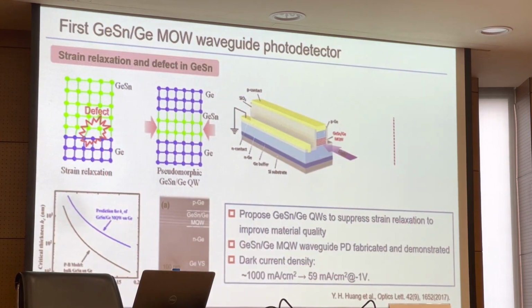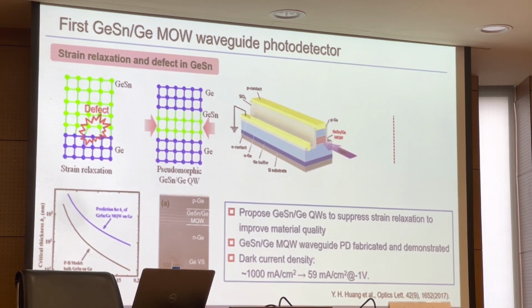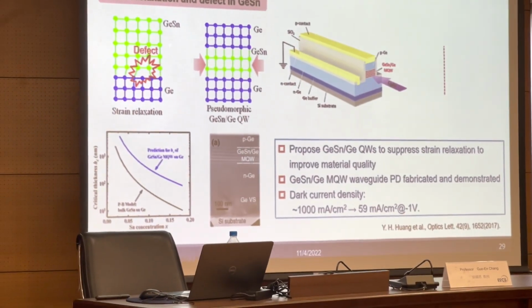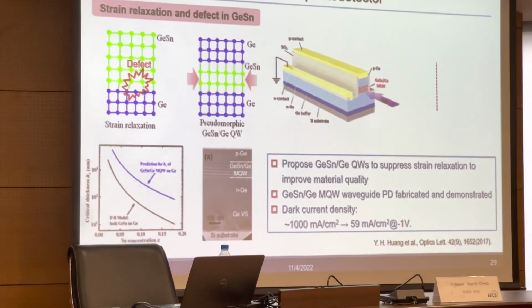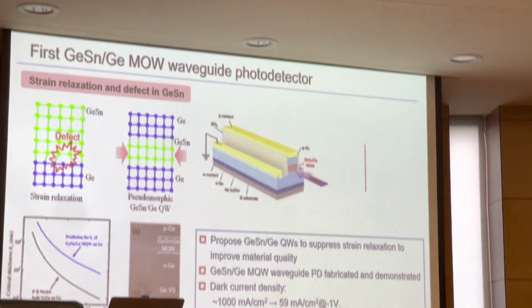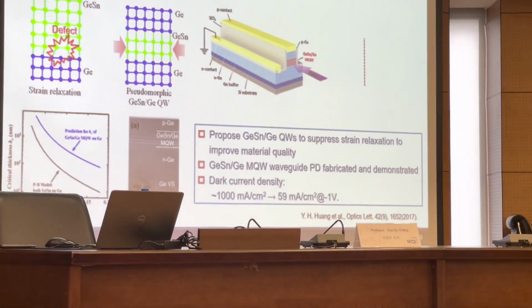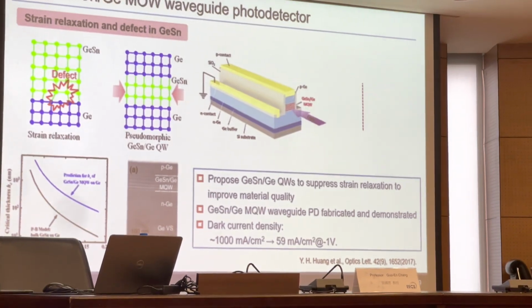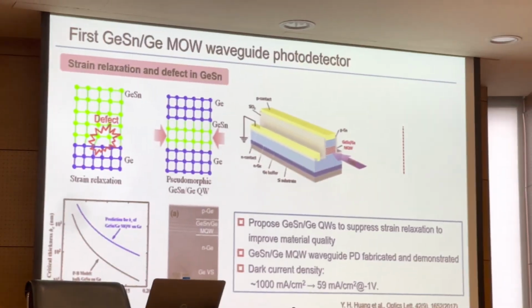So we are thinking, what is the problem that induces dark current? One problem is when we grow germanium tin on germanium, as we increase the tin content, the lattice mismatch between germanium tin and germanium becomes larger.